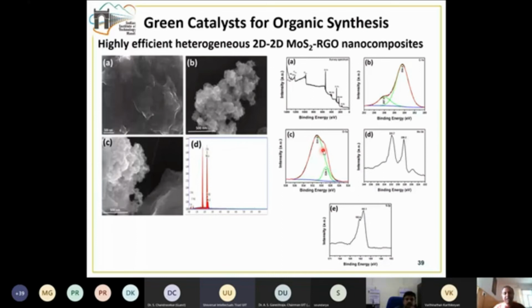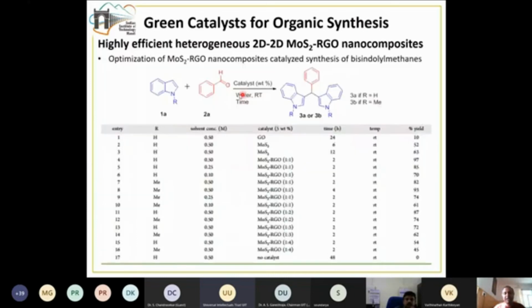Then we used this material as a green catalyst for the synthesis of bis-indole methanes. So we took these reactants with a certain percentage of this catalyst in water. All reactions were done at room temperature for different intervals of time in order to obtain these bis-indole methanes. And this is the optimization table, and we could see that MoS2 with rGO in 1:1 composition at 2 hours at room temperature is giving a 97% yield of this final product. It's a very good thing.